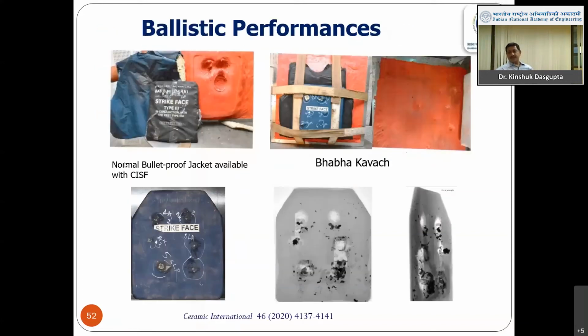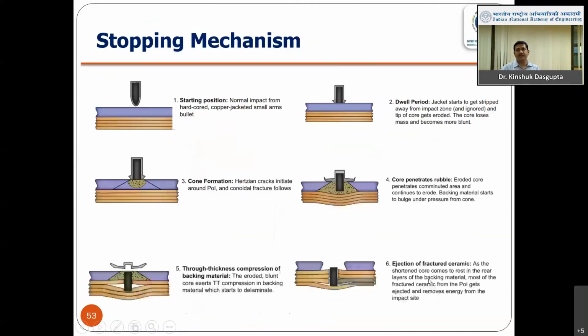So I'm just giving the summary of the results. This was the normal jacket which our CISF people used to wear, and you see this much dent, which is called trauma, very much visible, around 40 to 42. But when we used Bhabha Kavach, where carbon nanotube is used, you hardly see the backface signature. And under X-ray radiography, these bullets are all fractured. See, 6 bullets have been shot here, 3 SLR, 3 AK-47 hard steel core, and all of them are fractured and captured here.